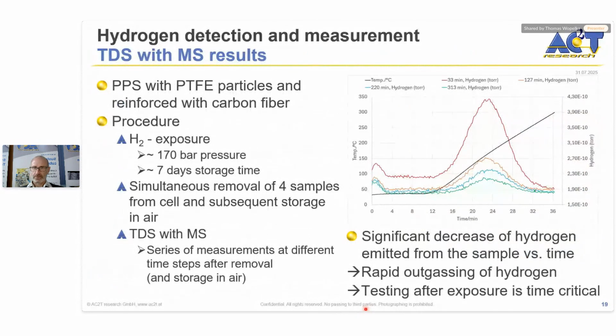So this is the result I want to present to you. Actually, it has been measured a few days ago. So I got the results this week and they are quite interesting. That's why I want to show it. We investigated here this PPS polymer with PTFE particles and reinforced carbon fiber. Four samples were stored in a high pressure hydrogen cell for a week with 170 bar pressure. And then the samples were removed from the hydrogen storing device simultaneously and were just stored in air for the next time. And we did a series of TDS measurements with mass spectrometry on those samples.